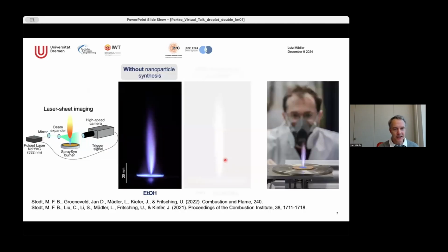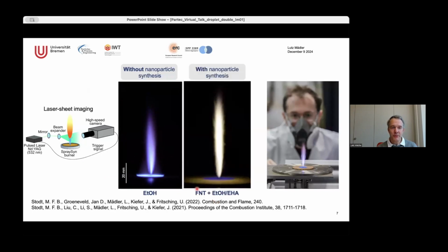And this is again Malte here, who just finished his PhD. And that's a very simple spray flame, simple in terms of there's no metal inside. So it's just ethanol burning as a spray flame, and it looks very nice. And if you put some of these metals, in this case, it's an iron precursor, but it doesn't matter. It's a similar story. The flame changes, right? Of course, flame color changes because these metals, they have their own spectra that they emit once they're excited.